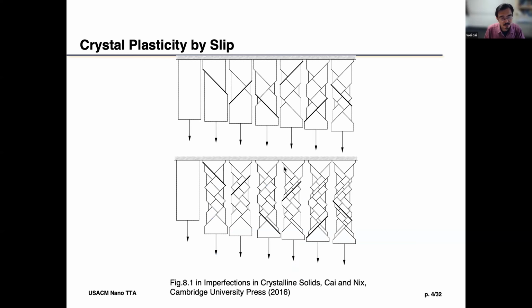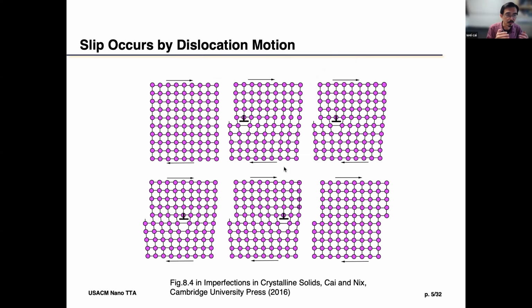Now, just as a general introduction, crystal plasticity happens by slip along crystal planes, but this kind of slip does not occur uniformly across a plane, because that would require too much stress. What happens is that part of the plane will slip, and the other part does not. At the boundary between the slipped and unslipped area, there are line defects that are called dislocations. The dislocations will propagate and make the slip area larger and larger, and that's how you accumulate plastic strain.